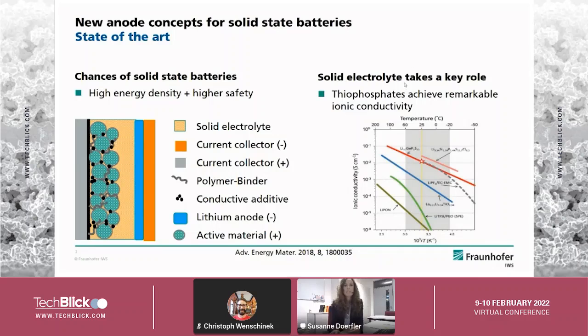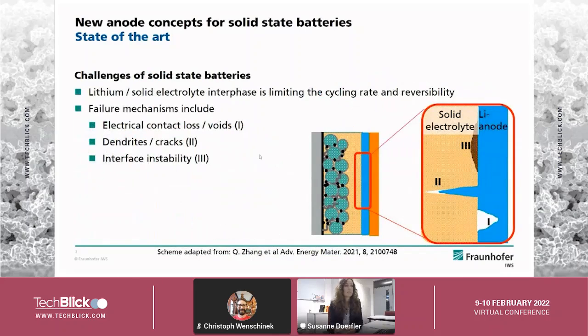Very important is the interface engineering between the NMC material and the solid electrolyte, and the separator layer is also a crucial point. Of course, interface engineering on the anode side, as we just heard in the last talk, is also quite crucial. So what are the issues? When we employ lithium as an anode, we struggle with the interface; especially the cycling rate and the reversibility of the electrochemical mechanism are limited.